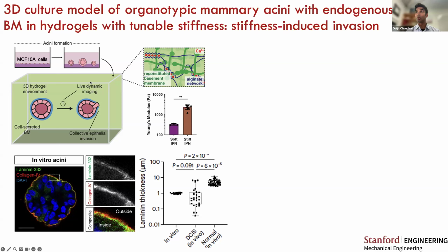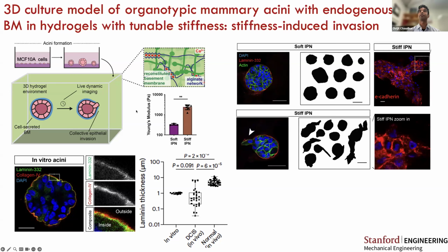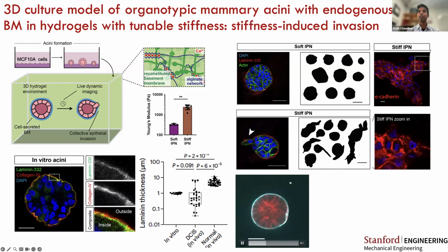So we then take these organotypic acinar structures with a basement membrane, and we culture them in hydrogels that were either soft or stiff. In the soft hydrogels, the clusters stay rounded. In the stiff hydrogels, we see that the cells invade collectively through the basement membrane. So in blue, what we're seeing in this video here is laminin 332, and in red, we're seeing the actin cytoskeleton. And you can see that the cells are invading and puncturing through the basement membrane and invading into the surrounding matrix.